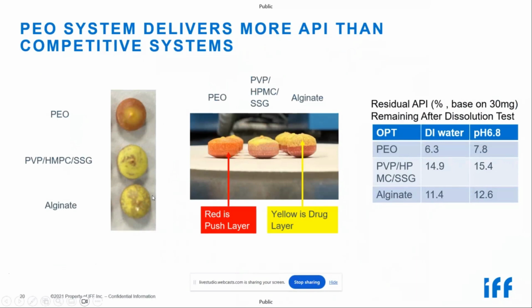So what we did is look at how much drug came out of each of these commercially available tablets. And again, the push layer is red, the drug layer is yellow. We could see that after, I think, a 24-hour time period, almost all the drug in the PEO containing tablet is pushed out. There's some remaining in both of the other tablets.